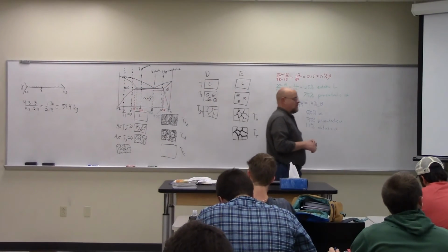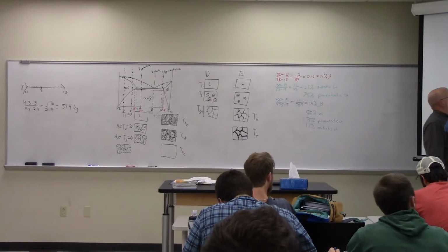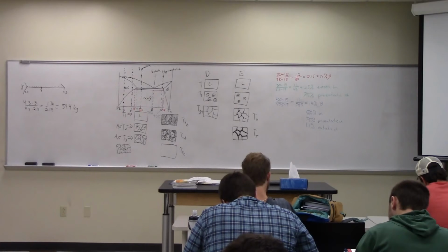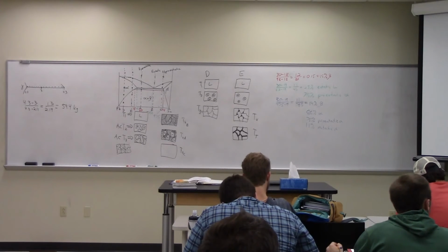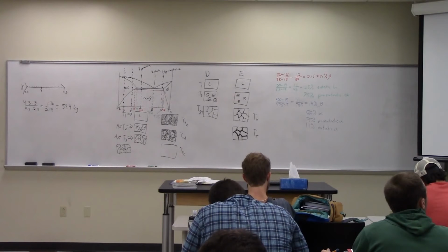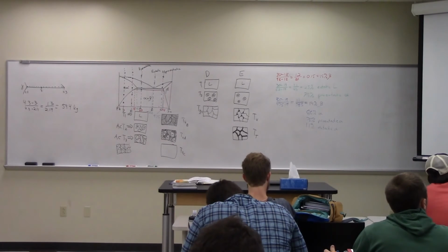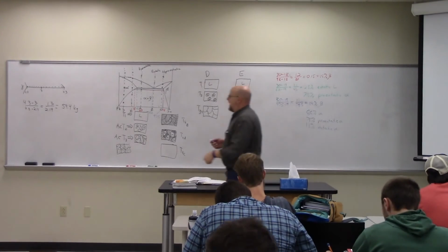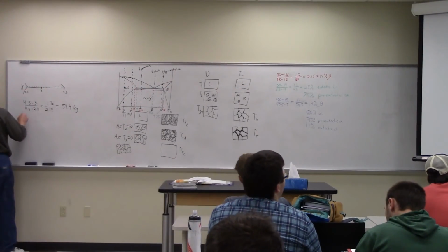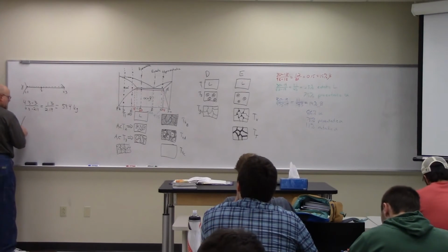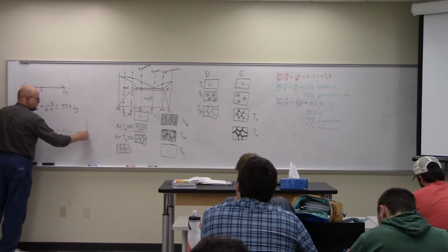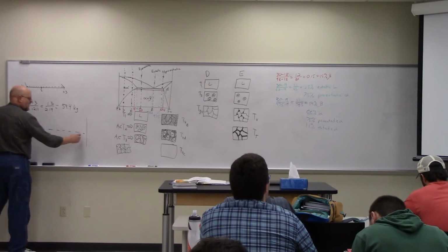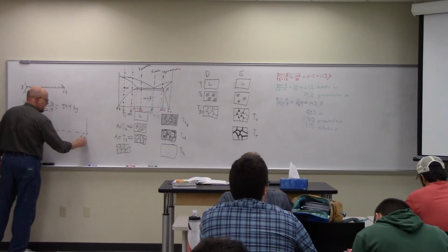Just do the inverse lever rule at the operating point? Right, the operating point here is 1,000, so I'm going to come down to this line. So I need to define the ends of my line. That end, we know, is 6.69. The cementite end is always 6.69. This end is conveniently 1.5. So now, I'm down here in this region. Well, this is at 3, this is at 1.5, and this is at 6.69.